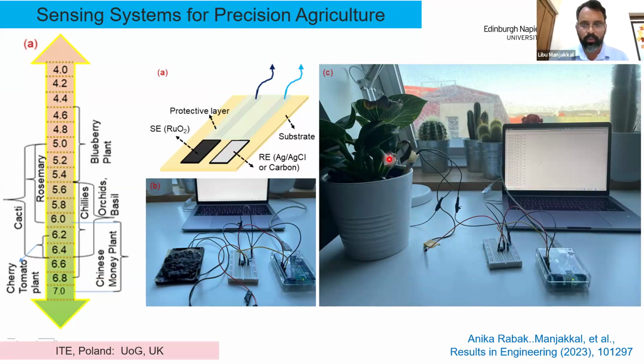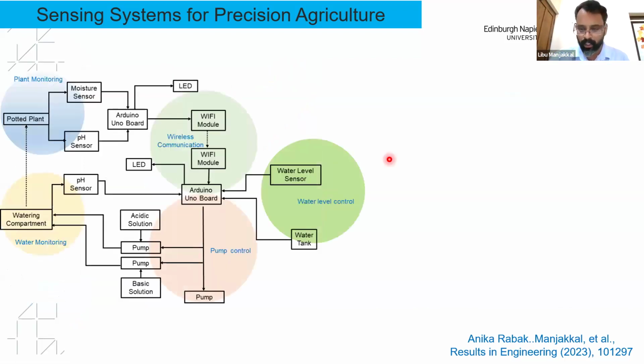This is one of the results we found, but the major problem we observed is that, when you monitor in a precision agriculture application, the major issue for soil monitoring is that the water content property changes. For example, when there is rain or when you pour a different type of tap water into that soil, the pH may change. In addition, with the buffer content in the soil, the pH will vary.